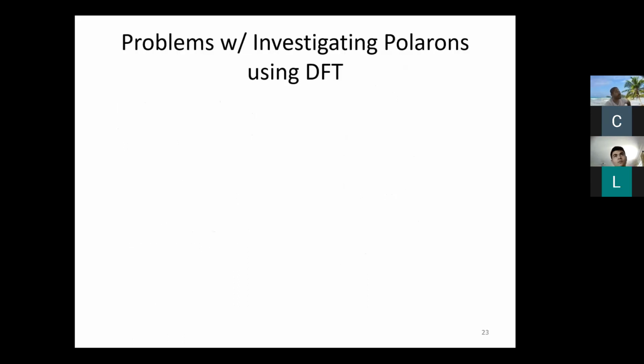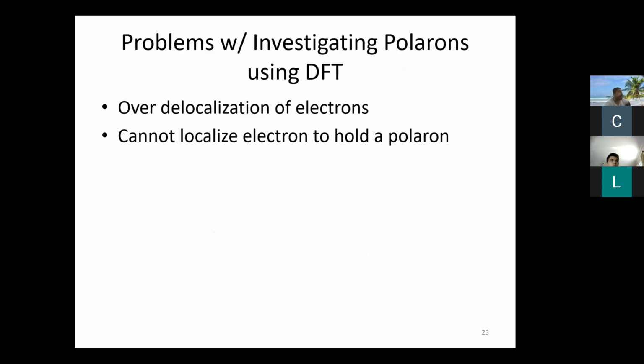So one problem with investigating polarons using the standard DFT methods is that in DFT, you tend to over-delocalize these electrons. As I mentioned, you don't incorporate proper exchange or correlation. So when you attempt to delocalize this in a real system, you'd see localization, but using this, you might not. And so you can't localize an electron to hold a polaron with this. The good thing is that there are solutions, or else I wouldn't be using it, right?